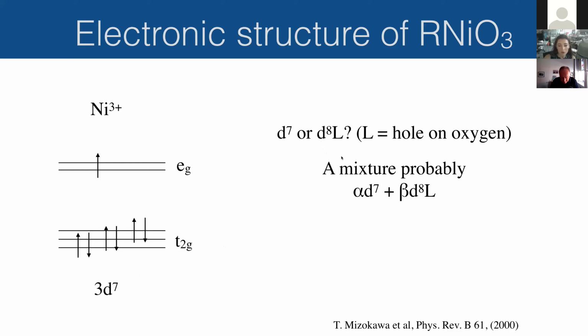And probably what you have in the end for the nickelates is that you have a little bit of D7 character and a little bit of D8L character. It's not a 100% charge transfer from the oxygen, but you have a mixture. And it's weighted by some factors, alpha, beta, that will probably change as you change the nickel, as you change the rare earth nickelate.